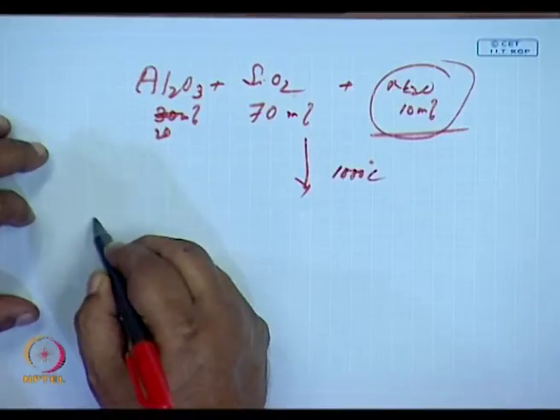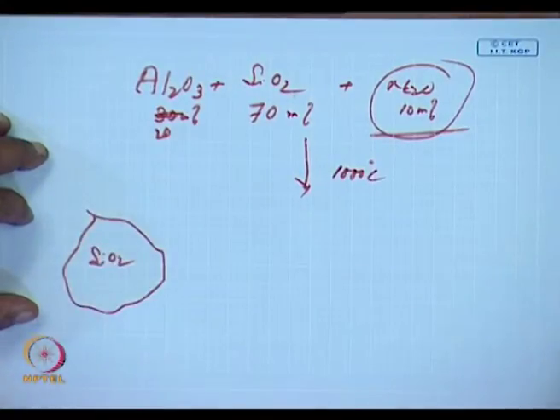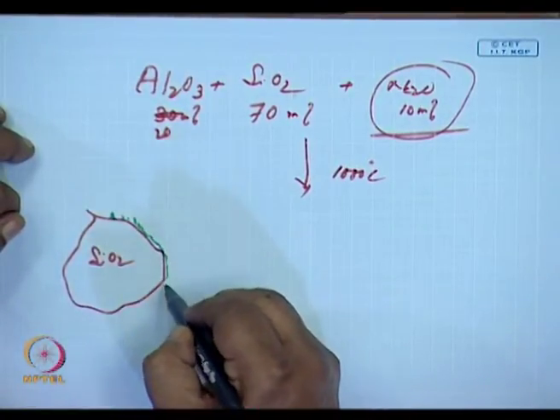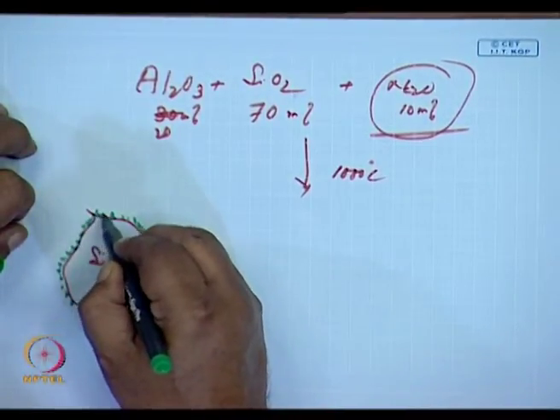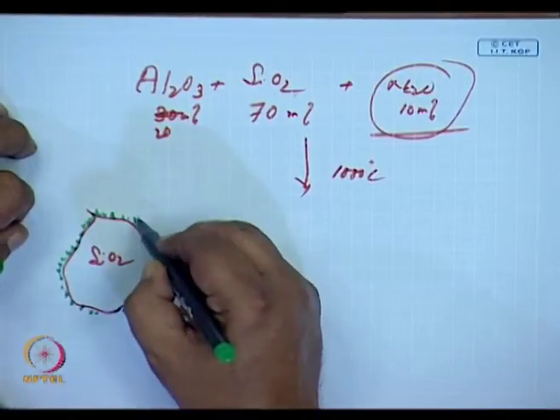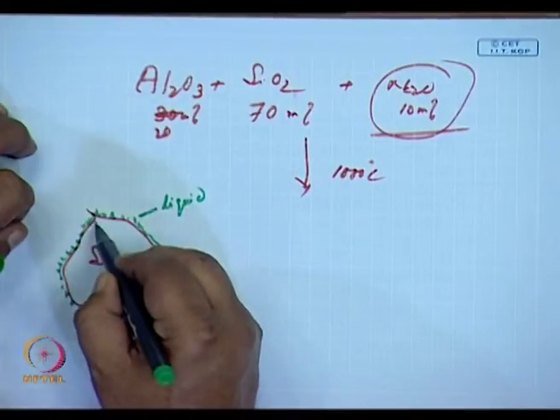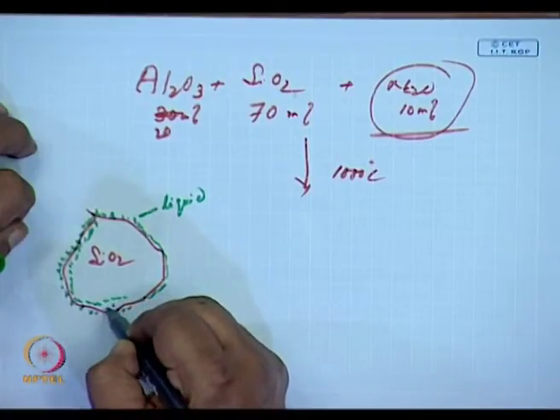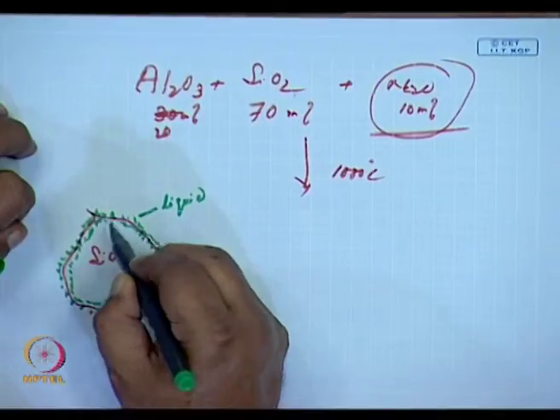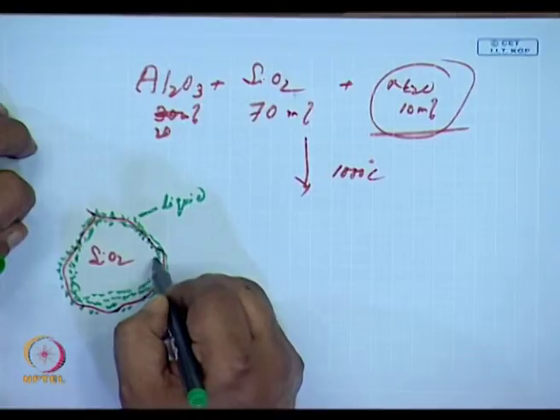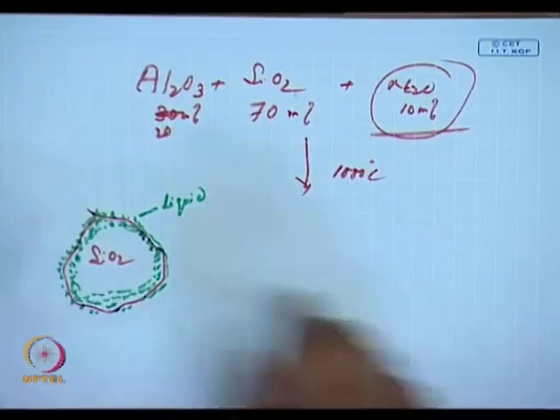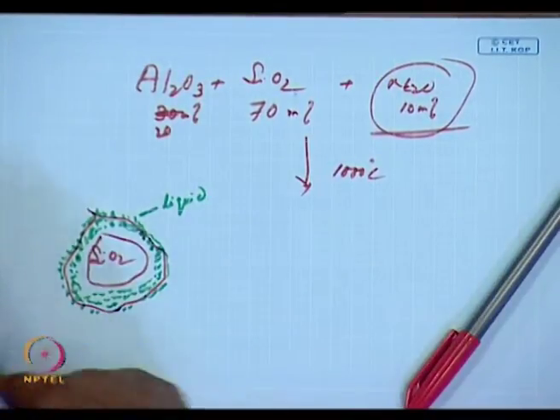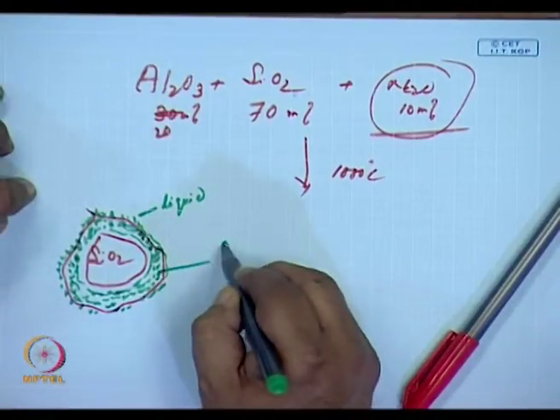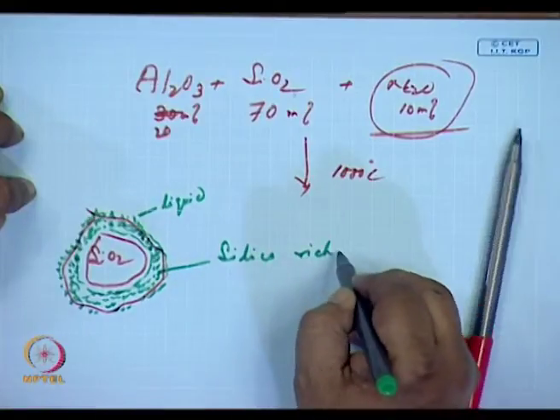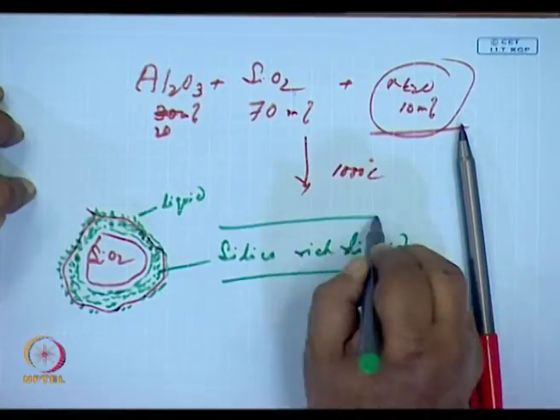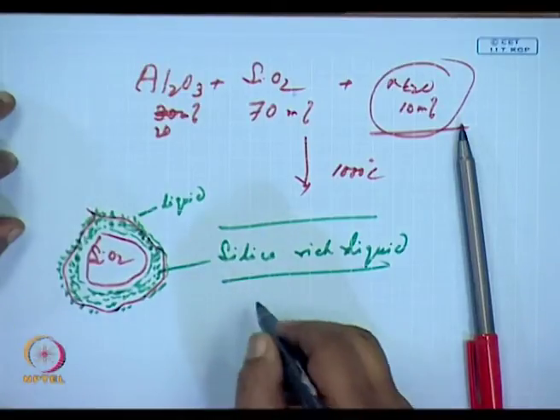What would happen is, if this was the original silica grain, and the molten sodium oxide was on the surface of this grain, it would react with the silica, leading to formation of a liquid. The more the reaction of the sodium oxide with the silica happens, the more the amount of liquid increases, with a concomitant decrease in the size of the silica grain. So what we end up with is a silica rich liquid. Now we have Al2O3 also.